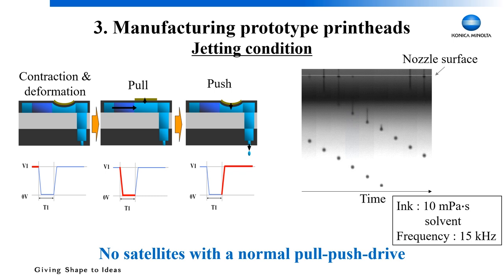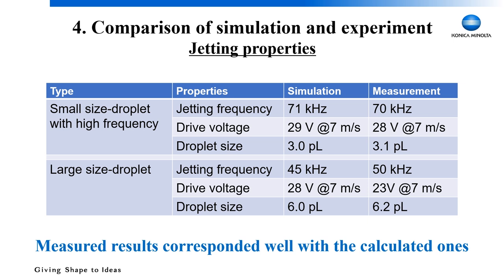Next is the comparison of simulation and experiment. This table shows the jetting properties of the simulated one and the measured one. We designed two different actuator types: a small size droplet with high frequency type and a large size droplet type. The former was designed for jetting frequency 71 kHz and droplet size 3 picoliters. And the latter was designed for jetting frequency 45 kHz and droplet size 6 picoliters. As shown in this table, the measured results corresponded well with the calculated ones. That means our simulation model can predict the jetting properties precisely.